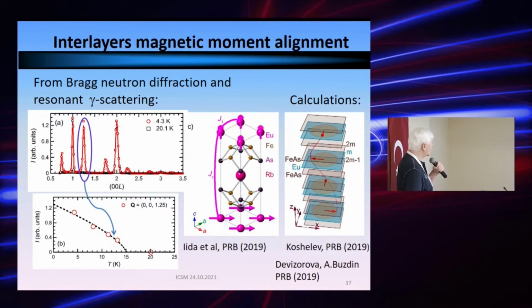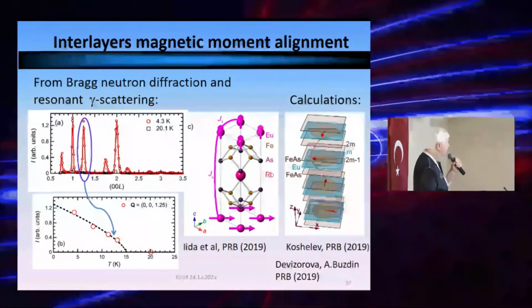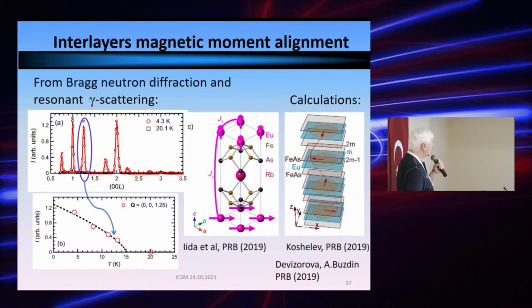This is accepted now as clear evidence for the 90 degrees orientation between the helices in the europium planes. How it happens is shown schematically in this picture: the magnetic moment rotates from one plane to another plane. It is also confirmed by calculations.